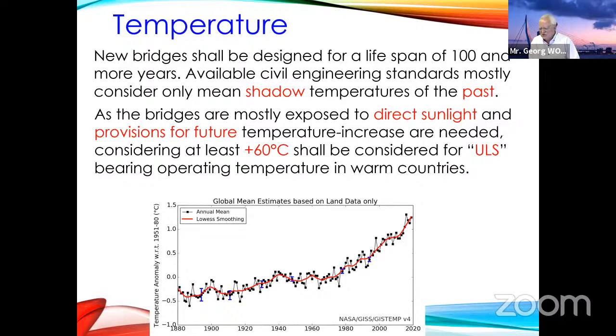I personally have seen big problems, for example, when the asphalt was applied to a steel bridge. You know, that asphalt had a temperature of nearly 200 degrees when it was put on the decks, and it warmed up the decks like crazy. So the bridges are exposed to direct sunlight, then sometimes you have a black asphalt on it, and you need a provision for the future. So from my point of view, in the warm countries, like most parts of India, you would have to consider at least something like plus 60 degrees to be on the safe side.